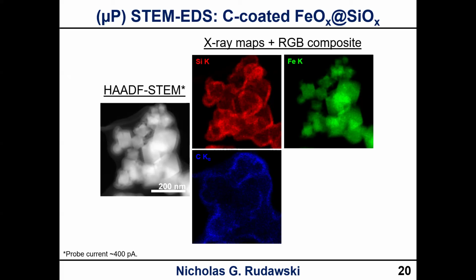So with the lamella, it is going to be flat. Okay. Assuming you're not tilting the stage a lot. So you don't have as many issues with depth of field. Okay. But with these nanoparticle clusters, that can be an issue. Okay. So this is again where microprobe STEM can really help you, because the particles don't usually sit flat, they cluster together, you have topographical variation, and so you can use it not just for imaging, but also for analytical work, okay?